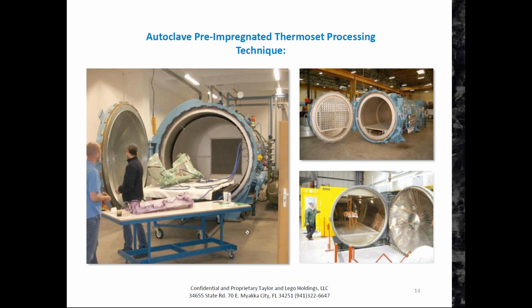You could spend an hour or 2 just laying up the material into the molds, vacuum bagging it, putting your intensifier in it. Usually these molds will utilize a silicone intensifier or some sort of a bladder type system. They'll get vacuum bagged. You'll load your valve. You will pull vacuum. You'll kind of massage everything in place. You'll put it in the autoclave, close the autoclave, apply 10 atmospheres to it. You'll cycle sometimes 2, 3, 4 times, depending on the resin system you're doing, different temperatures. You'll have a curve that you're going to follow. You'll depressurize the autoclave after that process has transpired. You'll cut the bag, throw away the bag, save the valve, pull the part, load the part into a machining center, and basically do your post-process trim and drill operations.